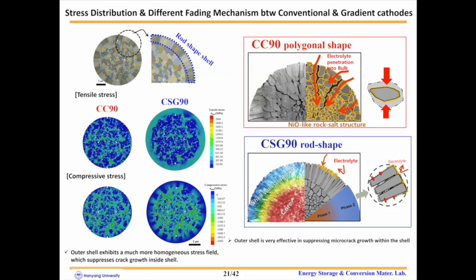To confirm the outstanding mechanical stability of the CSG cathode, stress distribution was calculated. This is the CC90 cathode. This is the CSG90 cathode. The encapsulating shell compressed the core and led to slightly smaller tensile stress in the core than that in the CC particle. The reduced tensile stress suppresses micro crack formation and thus improves the mechanical stability.